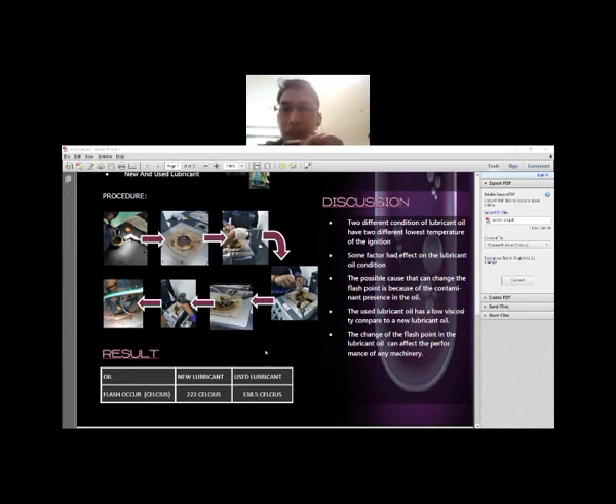So next, the result of this experiment. Based on the poster, we can see that two different values of the flash point occur. First, the new lubricant oil, whose flash point occurs at 222 degrees Celsius, and the other one is used lubricant oil, whose flash point occurs at 138.5 degrees Celsius.